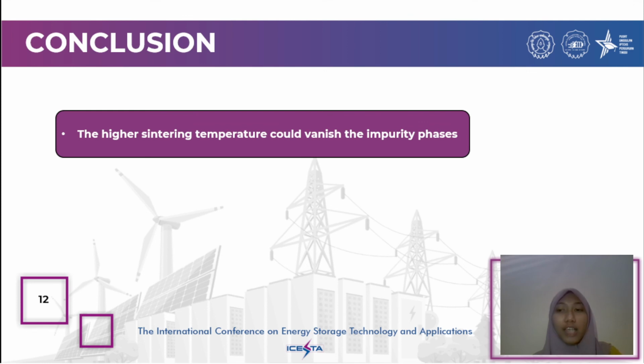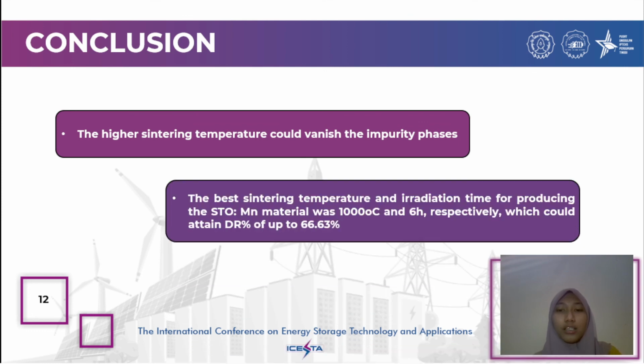Conclusion: the higher sintering temperature could vanish the impurity phases. The best sintering temperature and irradiation time for producing the strontium titanate doping mangan material were 1000 degrees Celsius and 6 hours, respectively, which could attain a degradation percentage of up to 66.63%.